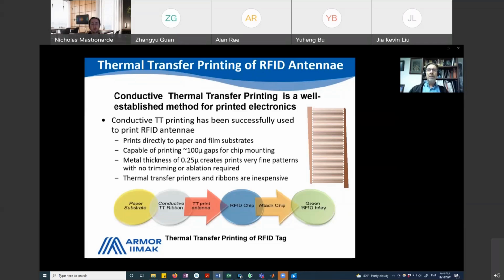The conductive thermal transfer printed antennae are ready to use immediately after printing, as I mentioned. With inkjet, the silver ink and inkjet printers are way more expensive. The quantity of silver required is about 10 times that of the aluminum used in the thermal transfer process. Copper-based inkjet inks are less expensive than silver inks, but these inks must be sintered before use. That is, gotten up to very, very high temperatures, and this adds additional capital expense and complexity to the operation.